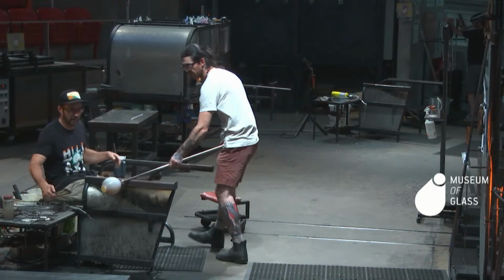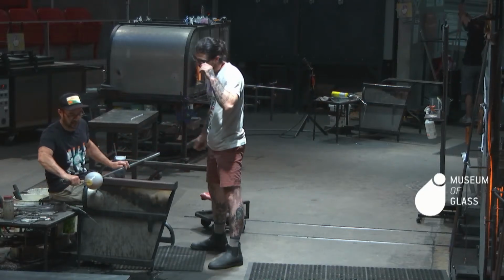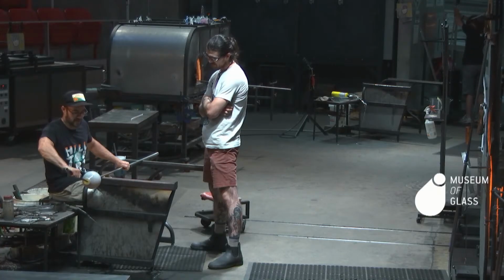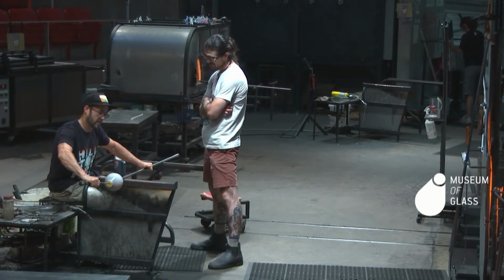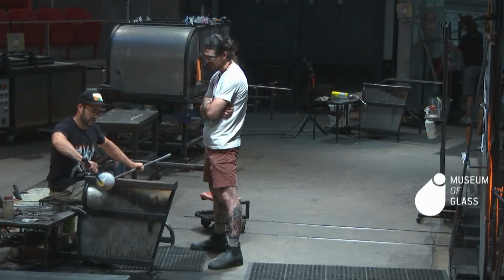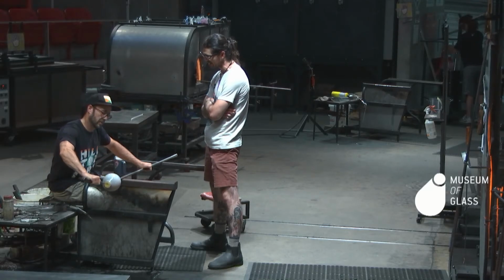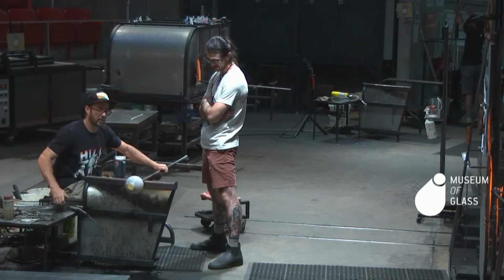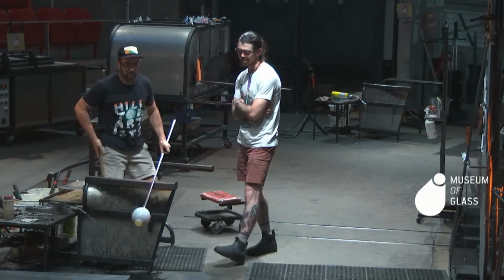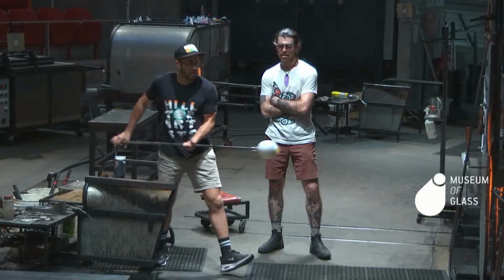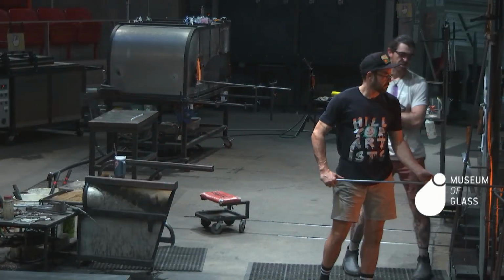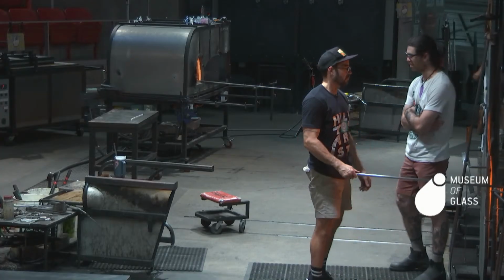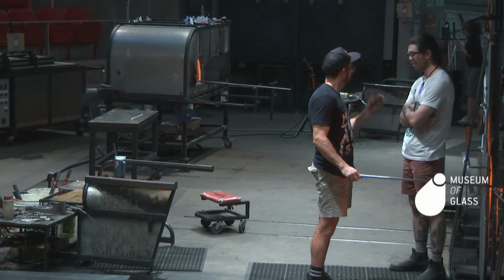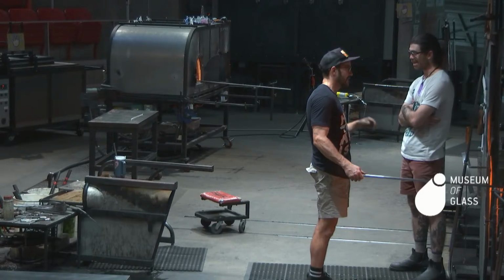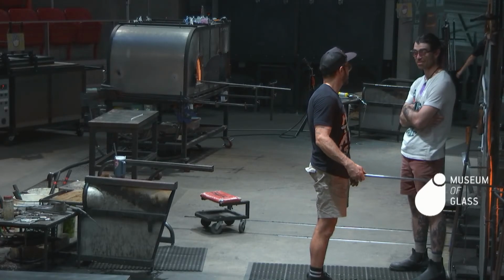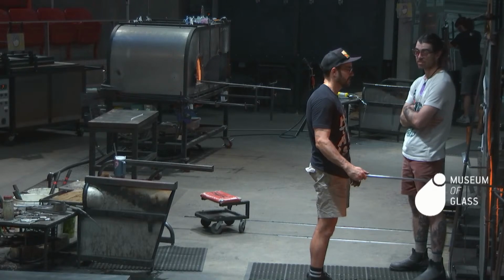And that's the last step for making our stuffed cup. So this cup is going to go into the annealing oven over there and cool down overnight. Once it's cold, they'll take it in the cold shop where they can grind and polish the glass. And then, on another day in the shop, they'll put that back into the annealing oven, and instead of cooling it down, they'll do it in reverse. They'll heat it up slowly. That way they can take it out of the annealer and put more glass inside of it, and that will keep the raw color on the outside. They want to keep the colored glass on the very outside of it.